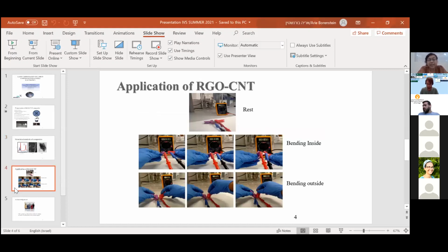So next come the applications of the RGO-CNT composite. We have the GO-CNT slurry. We can put it on the PET film, and after the laser carbonization, it becomes the RGO-CNT. The characterizations of the electrode can be done in the rest state and in bending inside and bending outside. When it's bending inside, you can see the resistance increases and the conductivity decreases. But when it is relaxed, it comes back to its rest position. Whenever the electrodes are bending outside, the conductivity increases and the resistance decreases, as you can see in the picture, which is totally reversed compared to when the electrodes are bending inside.